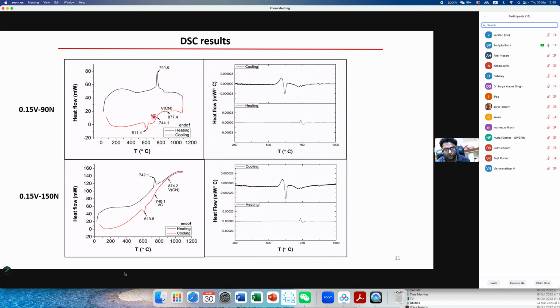But in case of cooling, we actually got three different humps. This is the derivative of DSC, and this is where we are expecting vanadium nitride precipitation, because in this steel only this can precipitate. There are no other elements to precipitate, or any phase transformation. So this may be vanadium carbonitride and this may be vanadium carbide.